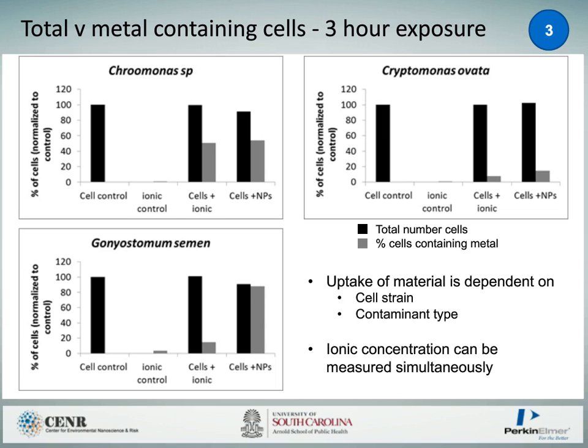When you go through to the cell plus ionic and the cell plus nanoparticles, you can see around 50% of our cells actually took up either some ionic material or some nanoparticulate material. This is actually in contrast to the other 2 cell species. The one on the right-hand side, which is our middle-sized cell, only took up about 20% ionic and nanoparticulate material. 20% of the cells took any of this stuff up. And then if you look at our large cells at the bottom, which are about 60 micron cells, you can see that, again, the cells took up ionic and nanoparticulate, but much more of the nanoparticulate material is taken up than the ionic material. So here we can show that uptake of material is dependent on cell strain and contaminant type.